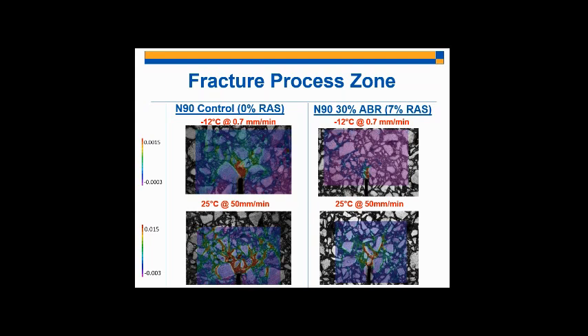Then we took our control mix, which is 0% RAS, and we tested basically its kind of deteriorated derivative, right, which is the 7% RAS, and it was tested at both -12 degrees Celsius and 25 degrees Celsius. And so you can see that, again, we can make an apples-to-apples comparison between the control mix and the 30% ABR or 7% RAS mix at both -12 degrees Celsius and at 25 degrees Celsius.